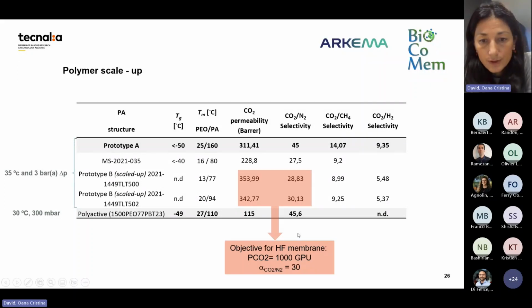Based on these results, we also can estimate, if we make the hollow fiber membrane with the optimal structure I showed before, which would be the properties for gas permeation we would be able to achieve. So it's about 1,000 GPUs and selectivity carbon dioxide to nitrogen of 30.